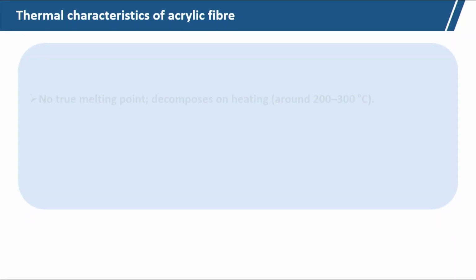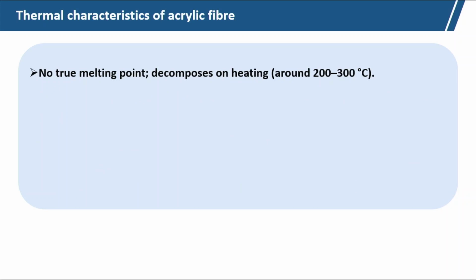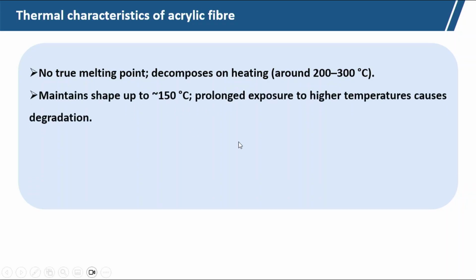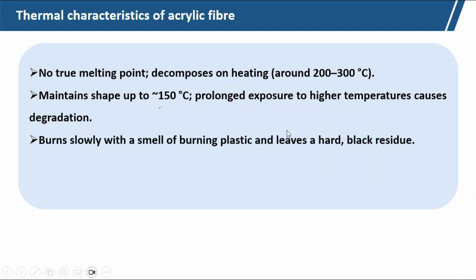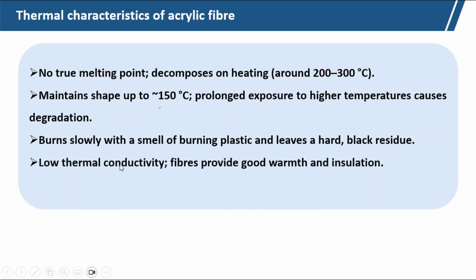The thermal characteristics: no true melting point, decomposes on heating around 200 to 300 degrees Celsius, maintains its shape up to 150 degrees Celsius. Prolonged exposure at higher temperature causes degradation. So, for low temperature application, acrylic is very good, burns slowly with smell. So, for fire protective application we can use modacrylic fiber. Low thermal conductivity, the fiber provides good warmth and insulation, that is why it replaces woolens, and for cold weather clothing we use the acrylic fiber also.